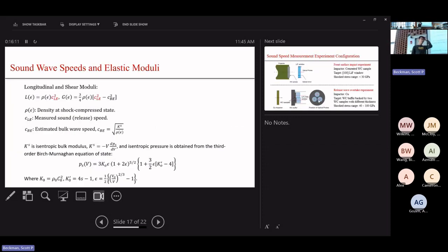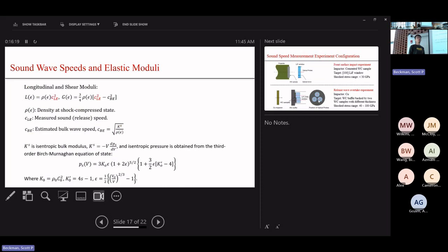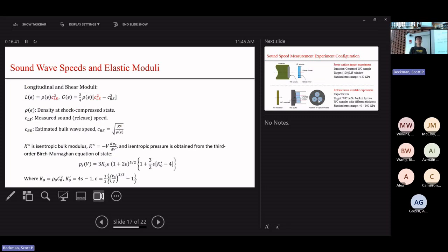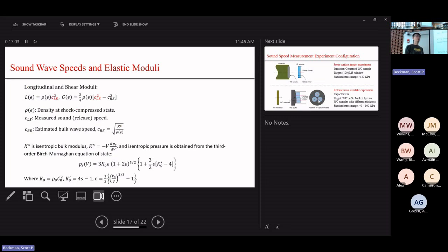The next set of experiments is sound speed measurement, which has been widely used in shock physics to investigate solid-liquid or solid-solid phase transitions. For example, if you shock silver metal to very high stresses, the stress can melt the silver to liquid, and since sound speed is generally higher in solid than liquid, you would see a drop in sound speed at that particular stress level as evidence of melting. We don't expect such melting or phase transition in our sample, but we can still use sound speed measurements to gain other useful information.